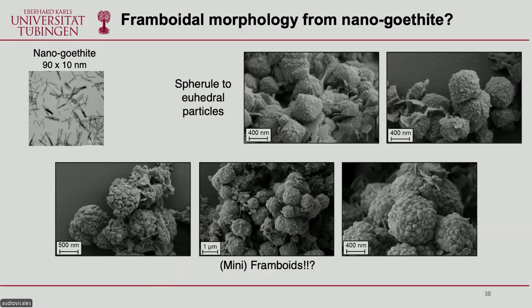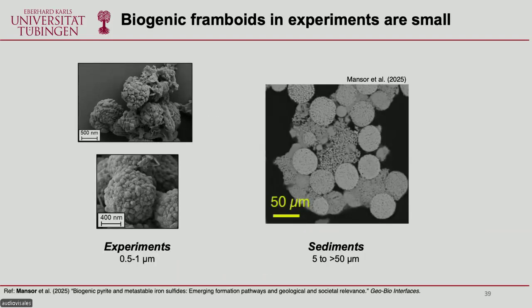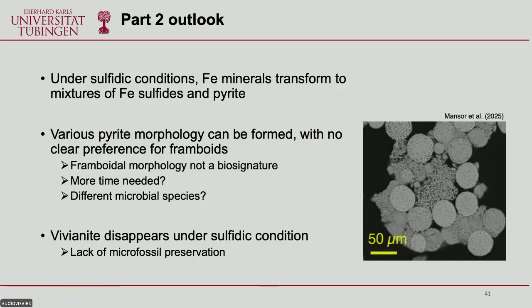But there is a problem because if you compare that to something that we typically see in the environment, they are extremely, extremely small. In the experiments, we see something that forms a maximum size of 1 micrometer. In the sediments, it goes to 5 to over 50 micrometer. And if you put this to scale, actually, this is the size of the framboids or mini framboids that we are forming. It's so small. And so that's the conclusion for part 2 for the moment.